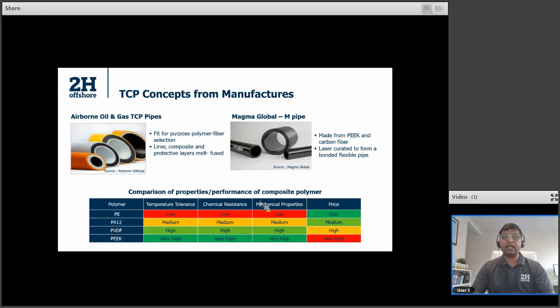On the other hand, we have Magma, which utilizes a combination of PEEK and carbon fibers to deliver a very robust structure, and this is laser cured to form a single bonded structure. And selection of this material depends on various parameters. We have a matrix down below where we have performance against different parameters, such as, for example, temperature.